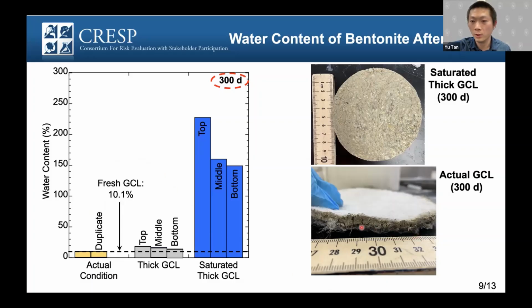So this is the figure of the actual GCL. It still has some deformation, but we still found that there are cracks between the bentonite. If the bentonite can swell, it can heal those cracks and become impermeable. If it cannot swell, we can imagine that the water can flow through those cracks and yield high hydraulic conductivity. And for the thicker GCL, the water content increased a little bit compared to the fresh GCL.